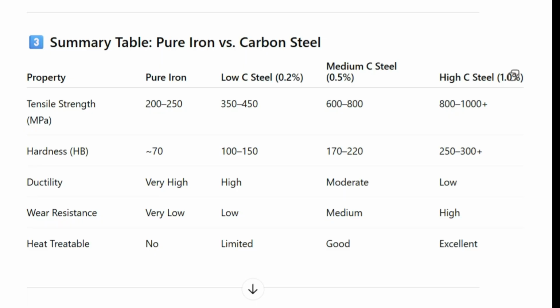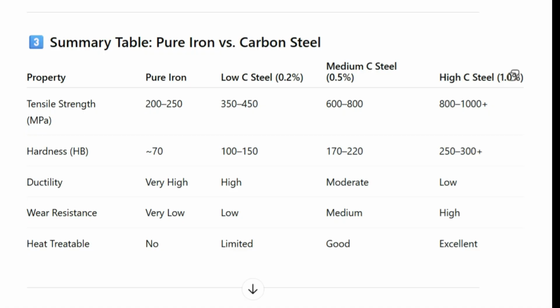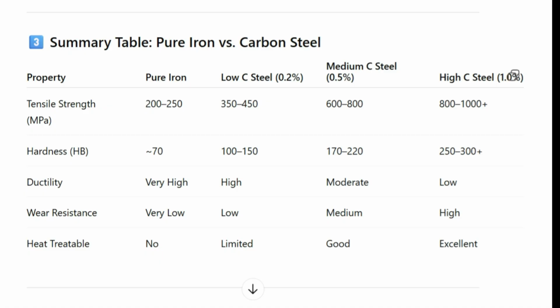And now just imagine pure iron, which we said is very ductile; it doesn't have much strength, but ductility is high. In low carbon, ductility is high, but it reduces to moderate in medium carbon and low ductility in high carbon. So the strength is going up, but you are losing ductility. Wear resistance, abrasion resistance: because it is hard, the high carbon steel will have a higher wear resistance. Iron will have lower, then low carbon will have low wear resistance, and then it increases with the percentage of carbon because hardness is more. Precisely this much you should know for the impact of carbon in carbon steel.